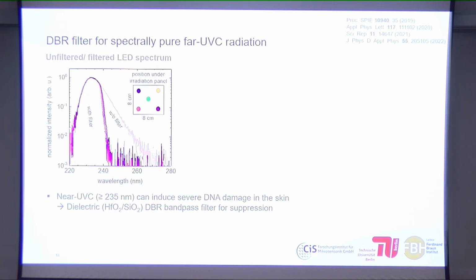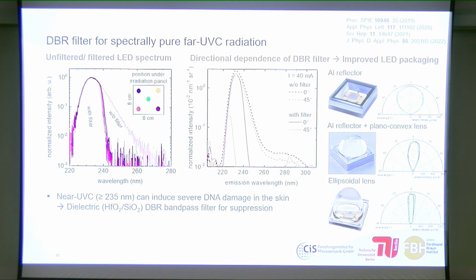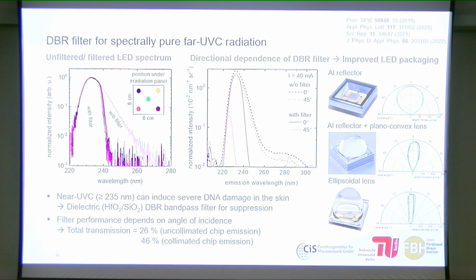So to do that, we have designed a hafnium oxide and silicon oxide DBR bandpass filter to suppress this long wavelength radiation, which you can see here. But what you notice is that we're also removing a lot of the intensity of the LED, and we find that these filters are really dependent upon the angle of incidence. If the light hits the filter at larger angles, less light is transmitted to the device, and you need more collimated light to have a high transmittance. To do that, we looked at our different packages and decided that the package with an aluminum reflector and a planar convex lens, with more collimated light, was the best option for the system. Therefore we could increase the total transmission from 26% without collimated chip emission to 46% with collimated emission.